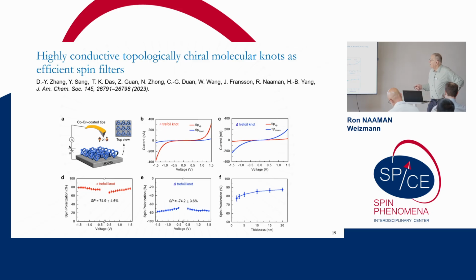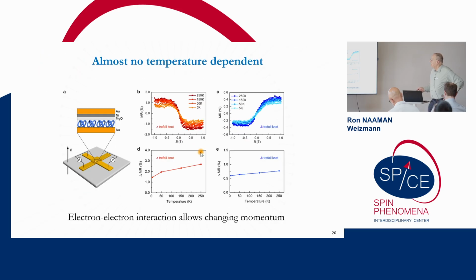We got very nice spin polarization, but then we measured the temperature dependence, and you see here that there is some increase of the polarization with the temperature, but it's not reduced dramatically. And our understanding is that it's a result of electron interaction that takes the role of electron-phonon interaction.